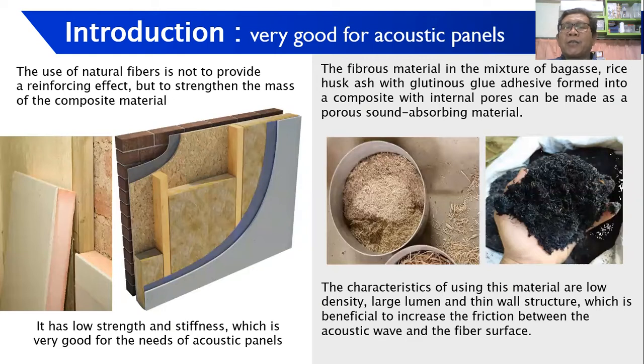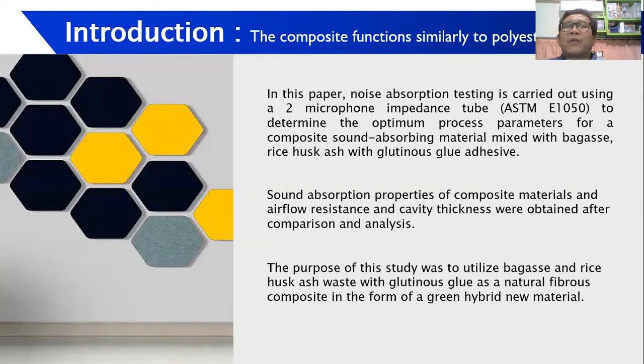The characteristics of this material are low density, large lumen, and thin wall structure, which is beneficial to increase the friction between the acoustic wave and fiber surface. In this paper, noise absorbing testing is carried out using a 2-microphone impedance tube to determine the optimum process parameters for a composite sound absorbing material mixed with bagasse, rice husk ash, and glutinous glue adhesive. Sound absorbing properties of the composite material, airflow resistance, and cavity thickness were obtained after comparison and analysis.